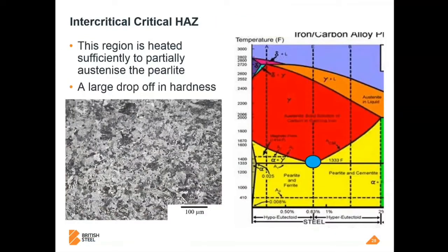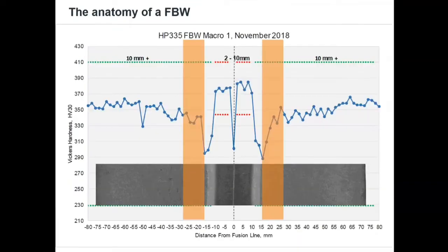Well, we're heating the steel up here to at and around the transformation point, and you decompose the pearlite, partially austenitize the steel, but not fully, and you spheroidize the pearlite that you do have, and you end up with a big drop in the hardness because ferrite becomes the more dominant phase. And then just here, the subcritical heat affected zone, the hardness returns back to the bulk.